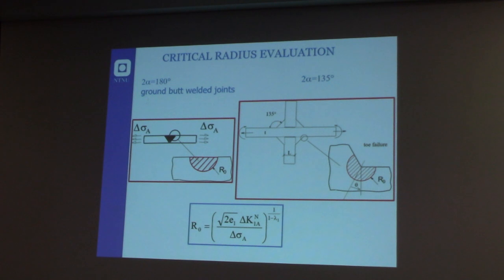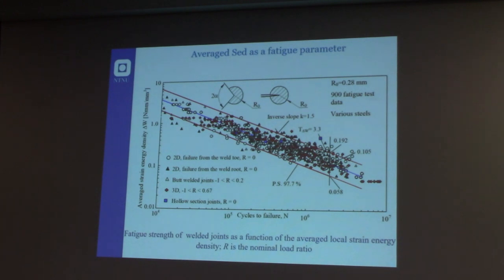In this case, we were thinking of fatigue, so we were referring to the critical value of the notch stress intensity factor at 5 million cycles, for example, and delta sigma A is the value of the unnotched material at the same number of cycles. In the literature, you can find these two numbers: this is the critical value for the unnotched weld material, and this is the critical notch stress intensity factor for welded joints.